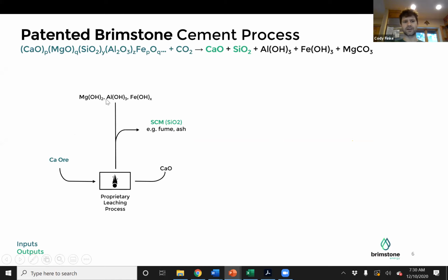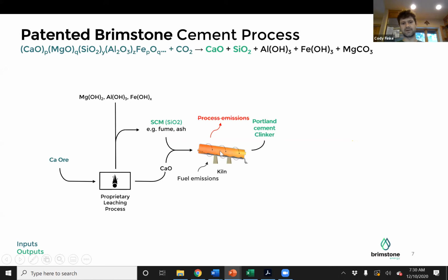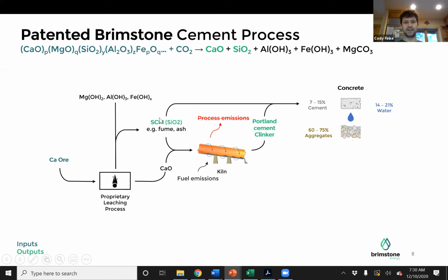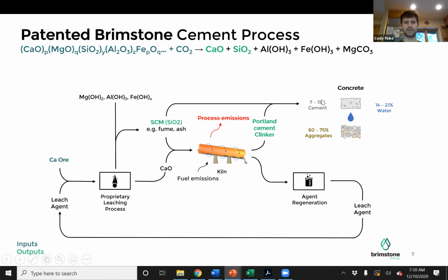And then the waste products, so any other oxides that are in the rock, which typically are magnesium, aluminum, and iron. We then put the calcium oxide in the kiln, just like the normal cement process. What comes out is ordinary Portland cement clinker, as well as conventional supplemental cementitious material. We mix those two together and make the exact same cement product that is made today. We then recycle our leaching agent, so there's no net consumption or production of the leach agent.